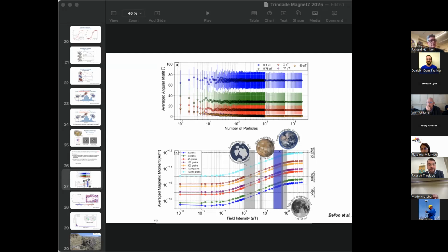And what's the main reason for the difference between those two papers? Is it just the way that you're treating the vortex state magnetization? Is that the key thing? That's one thing. For example, in the Burns paper, a grain had only 2 options, up and down. And here we have considered all the options for the orientation of the magnetic moments inside the grain and alignment to the field. So this is much more powerful when you compare to the up and down possibility.